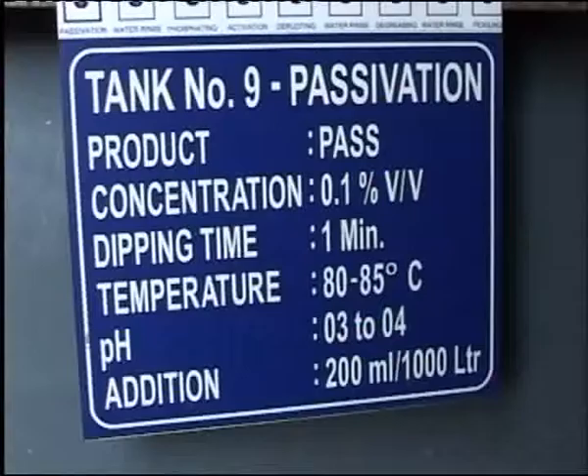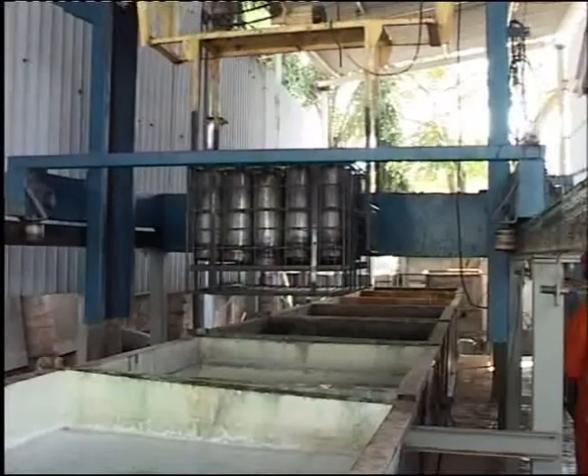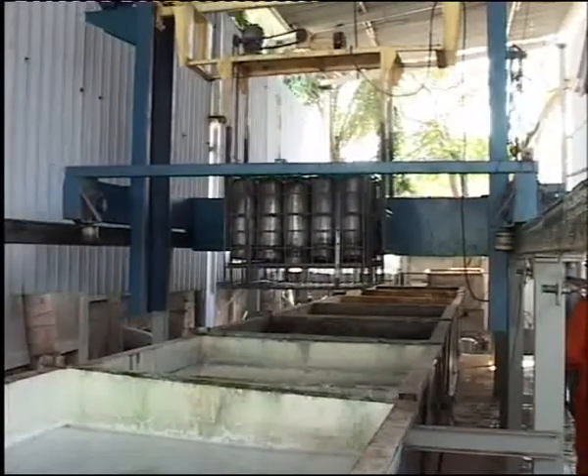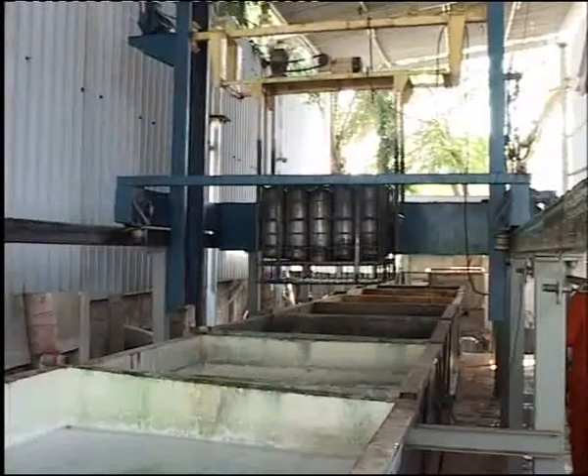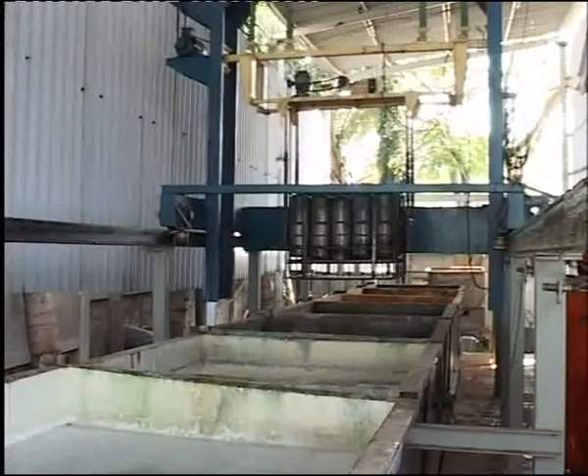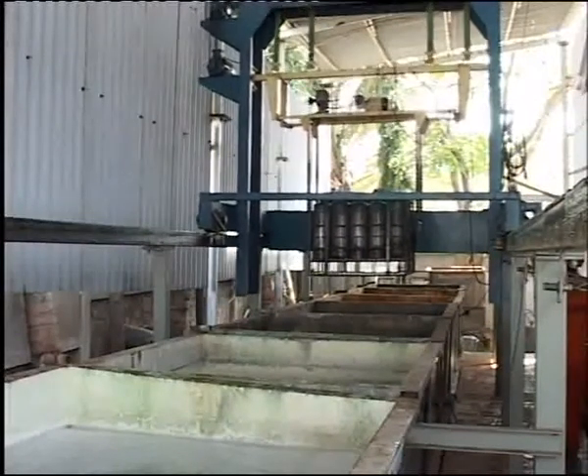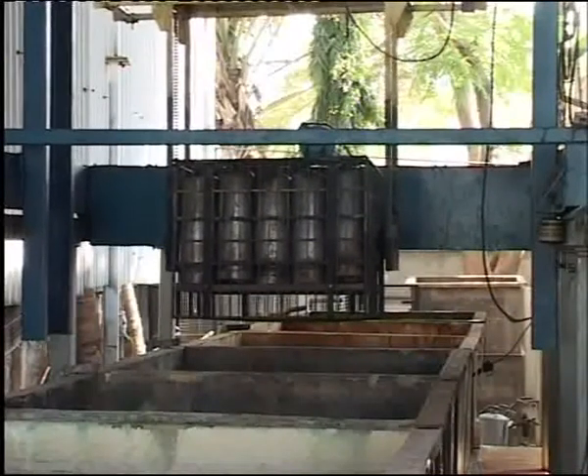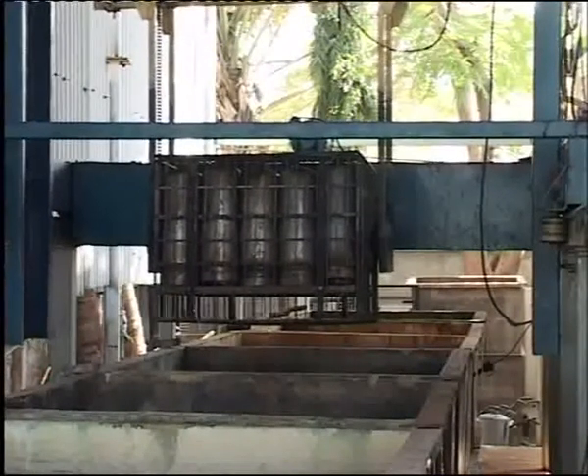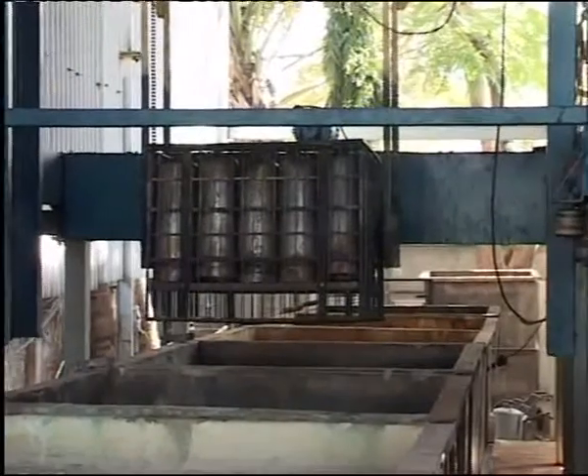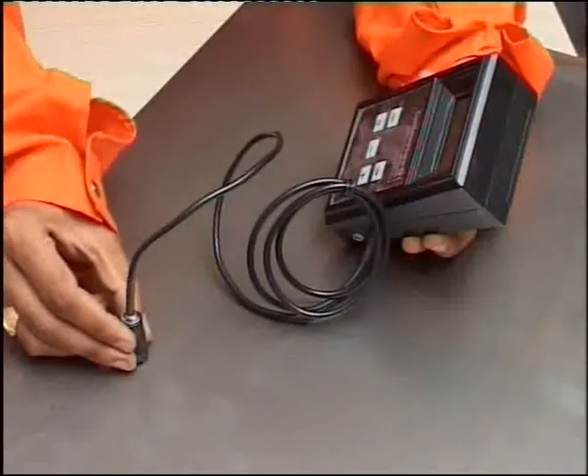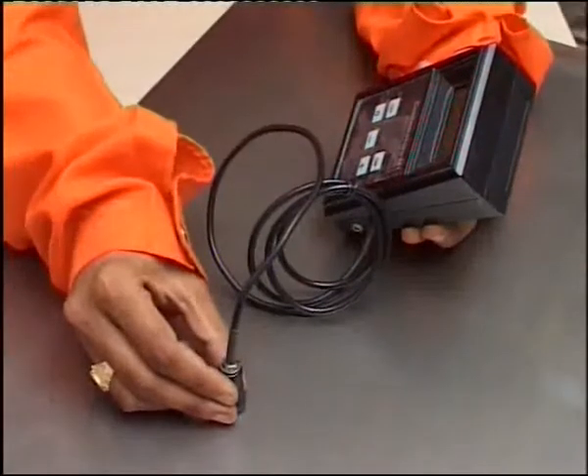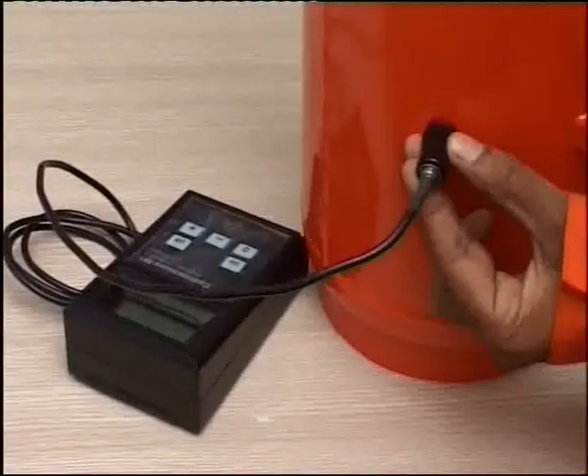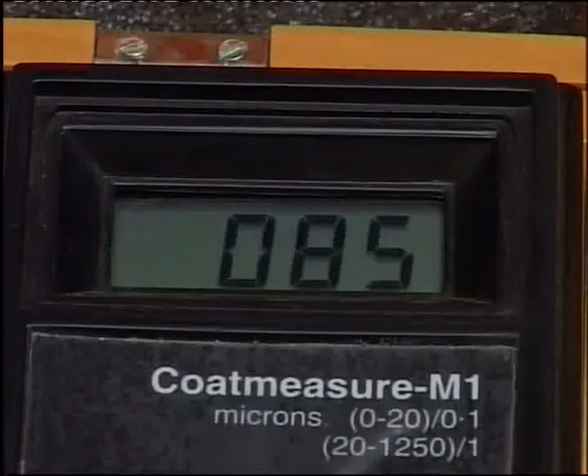A specially developed solution for passivation is for the post-rinse after phosphate treatment. This seals the pores of the phosphate coat and reduces the paint blistering under humid conditions and increases paint adhesion. This automation process increases the life of the fire extinguisher and helps to produce consistent material. QC engineers follow the process at every step to inspect the thickness of the cylinders by a high-precision digital coat meter.